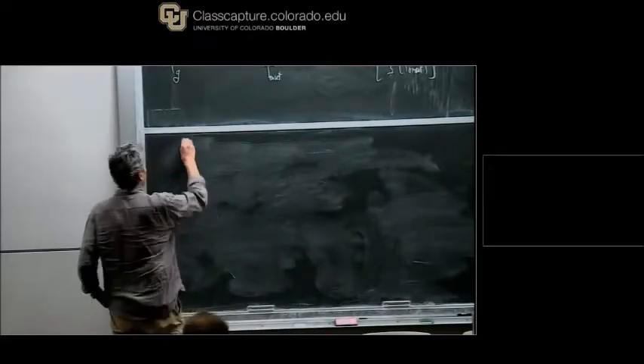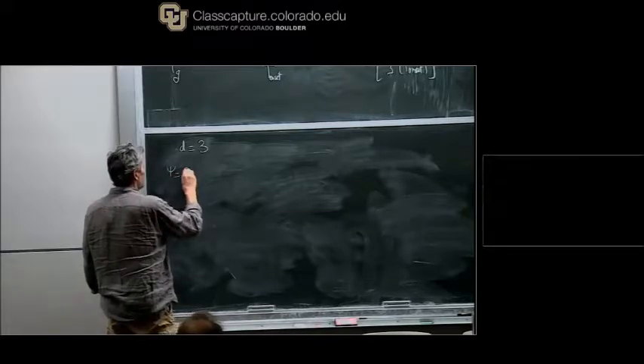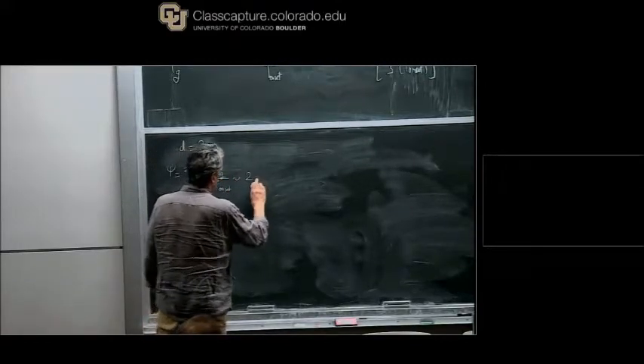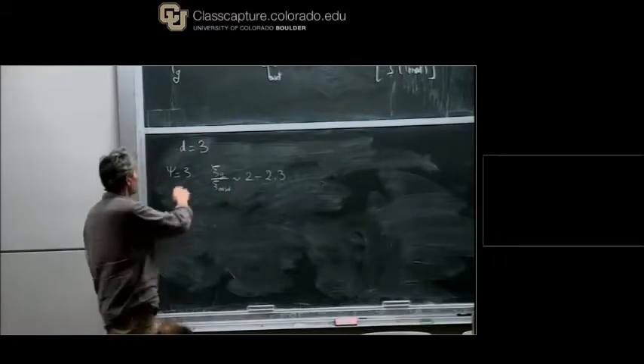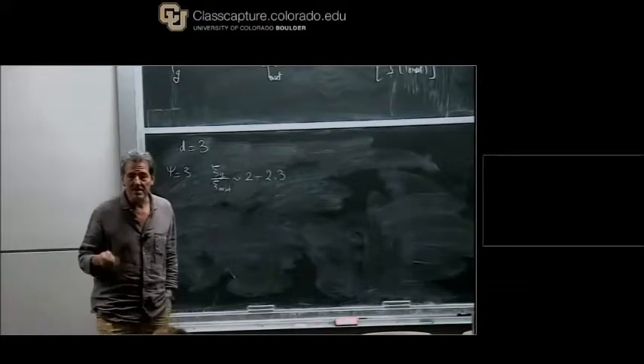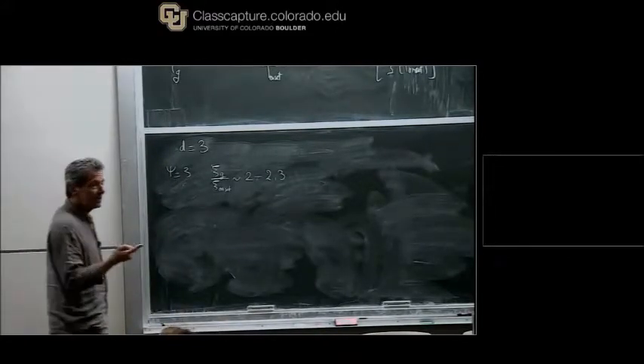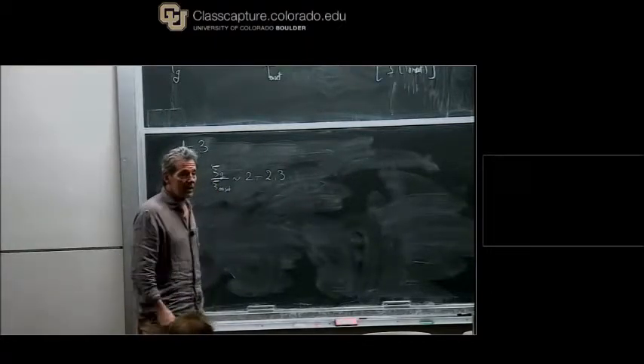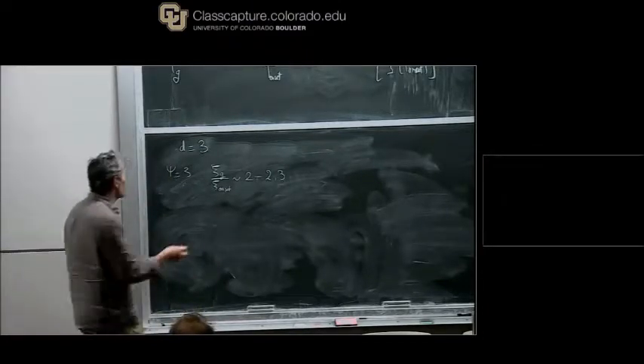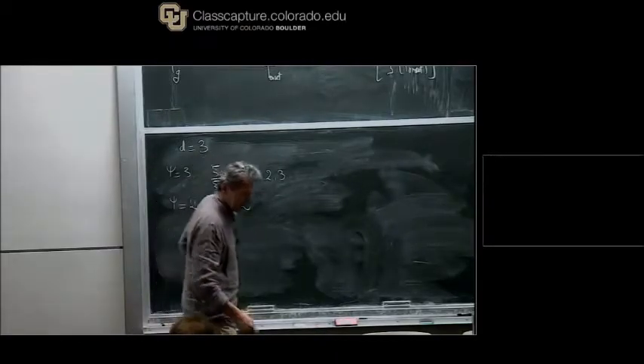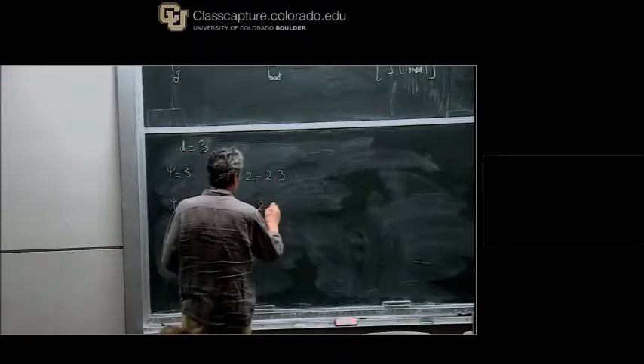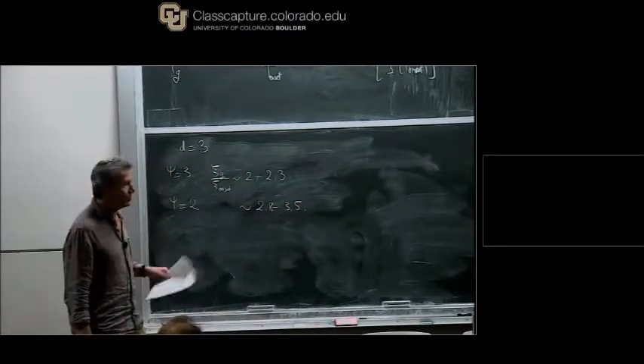Well, if psi is equal to 3, because now d equals 3, of course, I'm looking at actual liquids. So if psi equals 3, you see that the change of psi over psi onset is of the order of 2, I did 2.3. Okay, so this is, for instance, what you have in the bound. Okay, this is psi equal to d. So that means that if psi is equal to d, just changing the length scale by a factor of 2 explains the 16 orders of magnitude. All right. If psi is equal to 2, well, okay, it's a bit bigger. Let me give you the numbers, or you can do it by yourself. But it's around 3, so it's 2.8, 3.5. All right, it's a bit bigger. It goes to about 3.